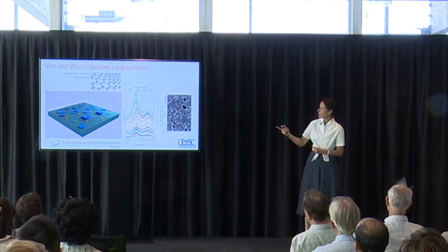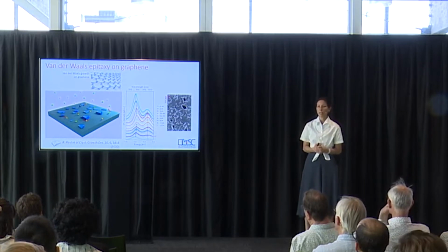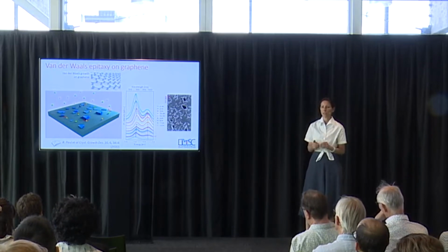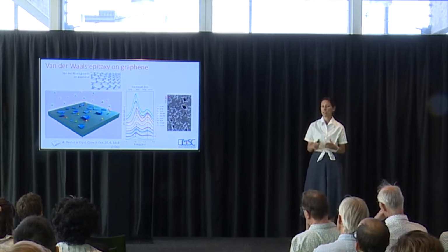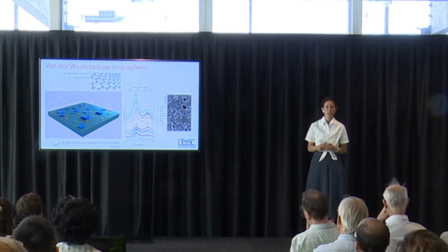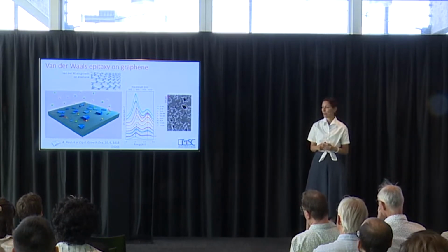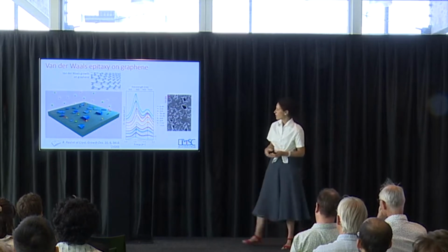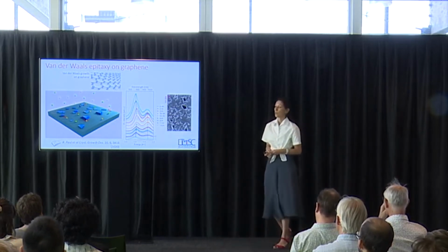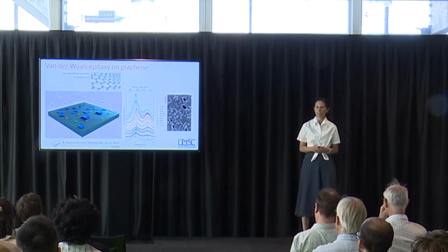But what you see on the left, they still luminesce. They luminesce below the band gap, which means that it is the defects that are giving luminescence. But these are defects that luminesce, which is probably better than the ones that are not luminescent. So it's about 1.4 and 1.3 electron volts, this is low temperature luminescence.